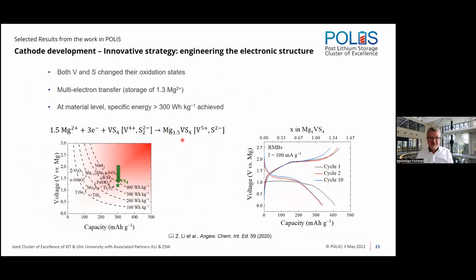And with this material, you could achieve storage of more than 1 electron per magnesium atom. In that case, it was 1.3 roughly. And this also enabled him to achieve specific energies beyond 300 watt-hours per kilogram. And in this diagram here, you also see that the comparison looks quite good if you compare it to other systems. Here on the right, you have a charge and discharge diagram.